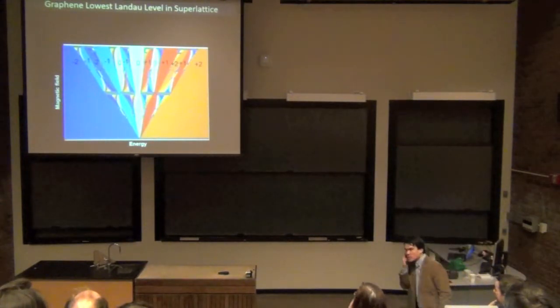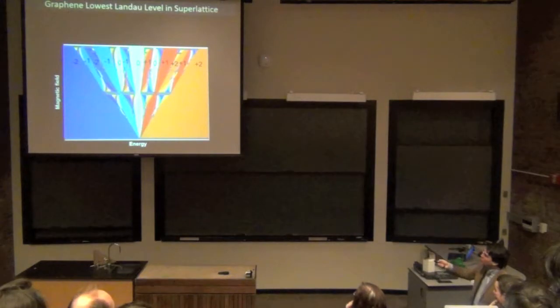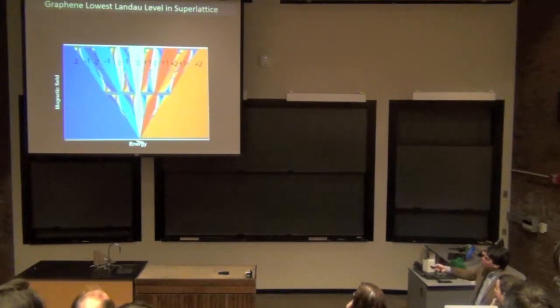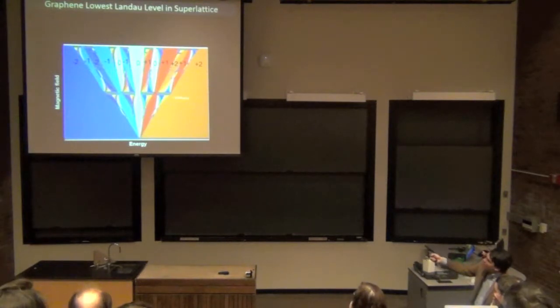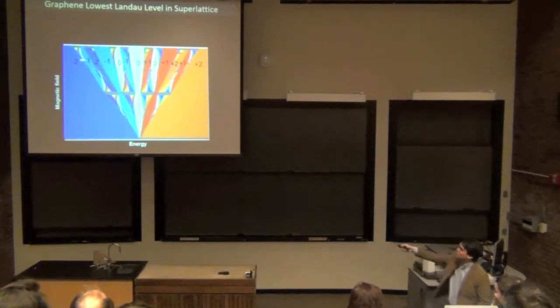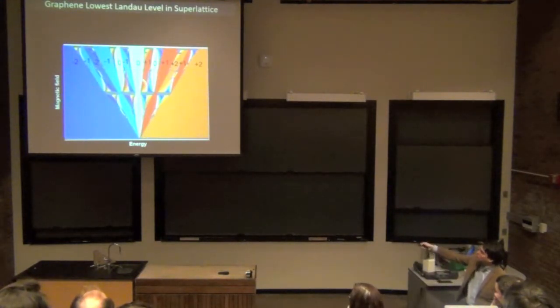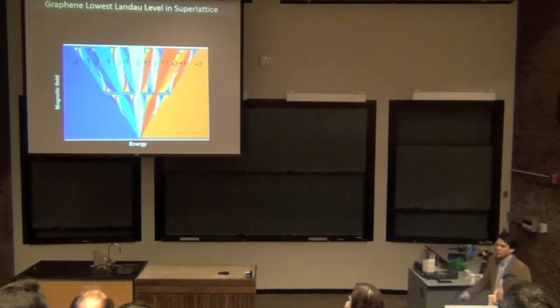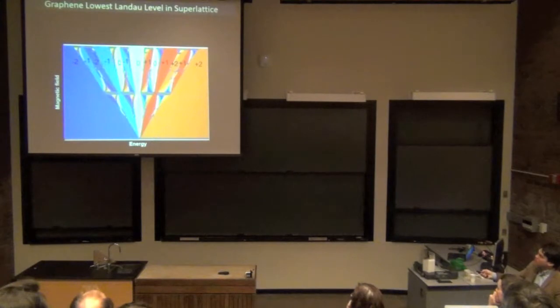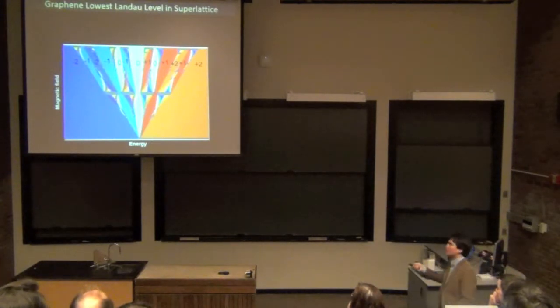And the important thing here is that when you're in this Hofstadter regime up here, at low fields you can see that it approximates the monotonic sequence. At high fields, if we look at the quantized Hall conductance, it follows this non-monotonic sequence. So instead of going 0, 1, 2, it goes 0, 1, 0, 1, 2, 1, 2 for electrons, and the same for holes. Okay. So that's the theory.